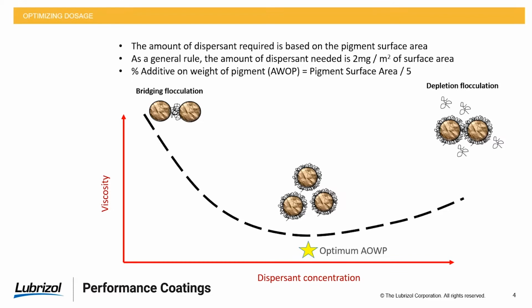The rule of thumb is that the additive on weight of pigment, which we call AOWP, the percent of dispersant necessary on pigment, is derived from taking the pigment surface area and dividing that by 5. So for instance, if you had a surface area of 100 meters squared per gram, divided by 5, we would recommend 20% dispersant on weight of pigment. So we don't make our recommendations based on total formula weight. We make our recommendations based on how much pigment you actually have. And we try to be pretty specific in terms of a starting point.